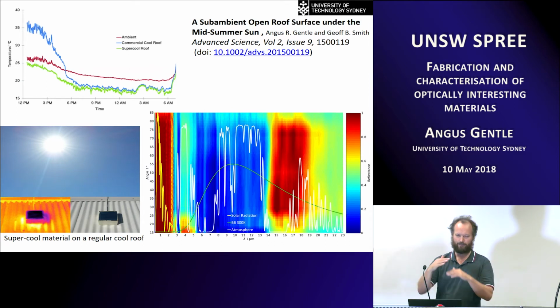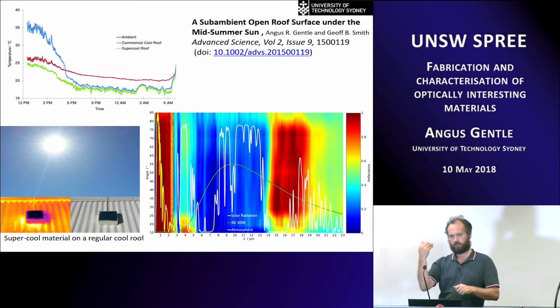There was a good way to do it, because they were doing it with these really complex multi-layer structures. This is based on a 3M multi-layer polymer, which is an extruded piece, and then we're doing a silver coating onto the back of it. The material normally gets used for back reflectors. It's called their enhanced specular reflector film.